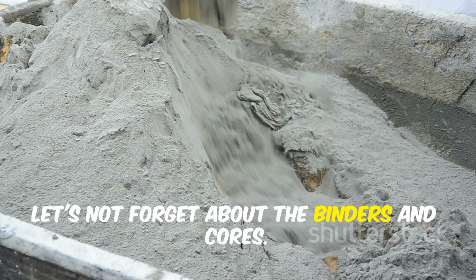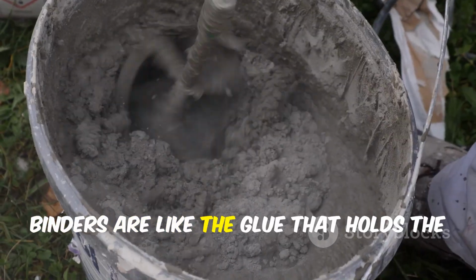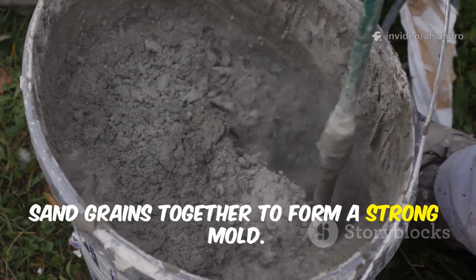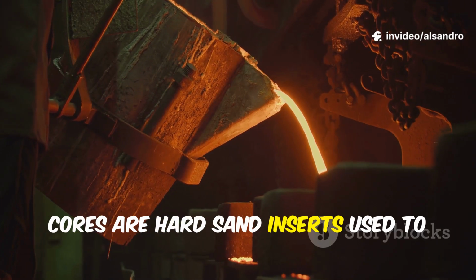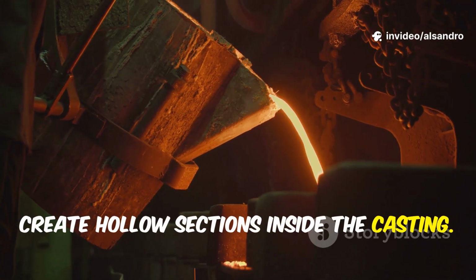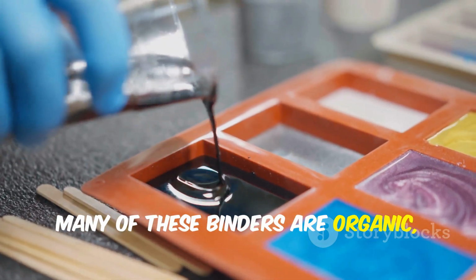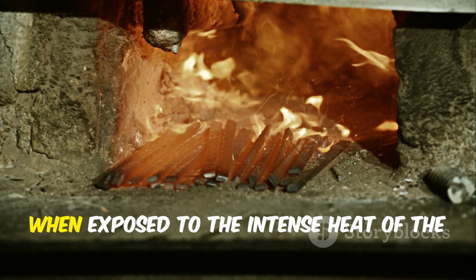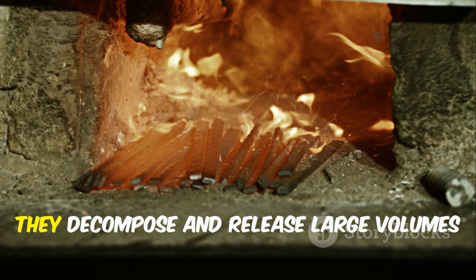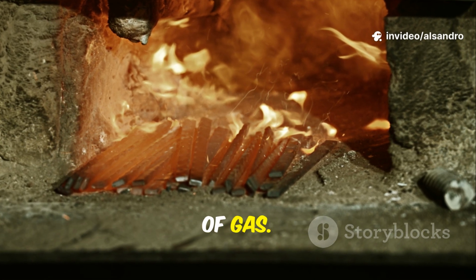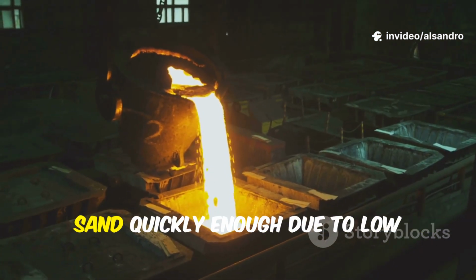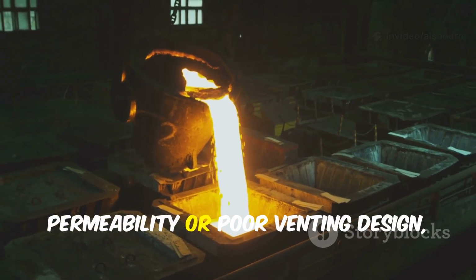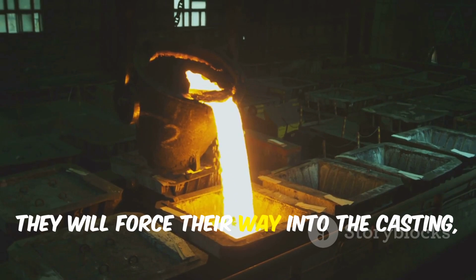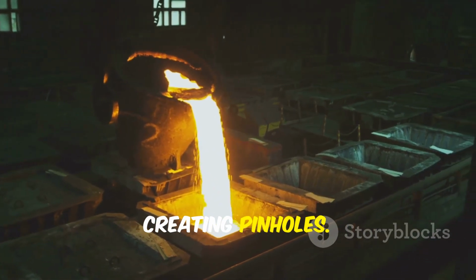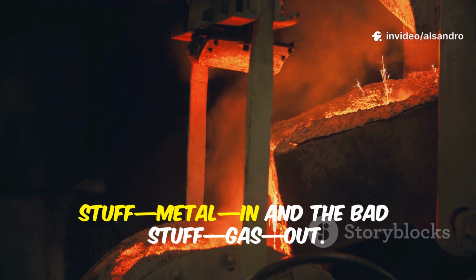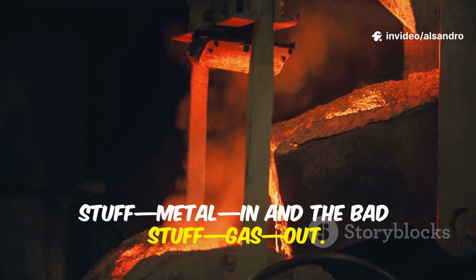Let's not forget about the binders and cores. Binders are like the glue that holds the sand grains together to form a strong mold. Cores are hard sand inserts used to create hollow sections inside the casting. Many of these binders are organic, carbon-based materials. When exposed to the intense heat of the molten iron, they decompose and release large volumes of gas. If these gases cannot escape through the sand quickly enough due to low permeability or poor venting design, they will force their way into the casting, creating pinholes. It's a constant battle to let the good stuff, metal, in and the bad stuff, gas, out.